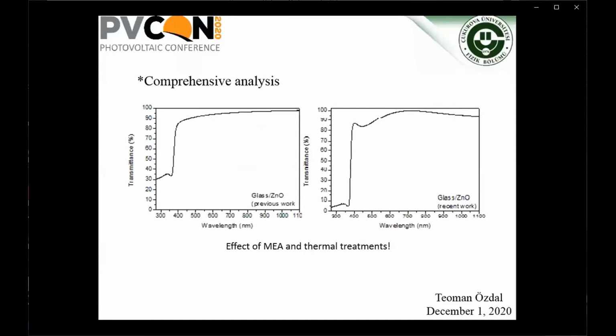As can be seen from the optical transmittance results, better transparent conductive oxide thin film was obtained. The new zinc oxide film gives an interference pattern indicating an increased crystallinity.